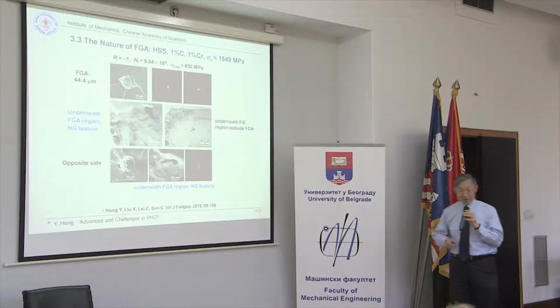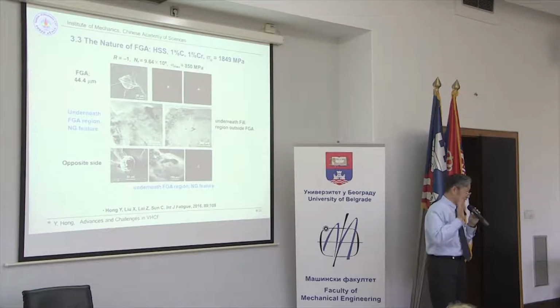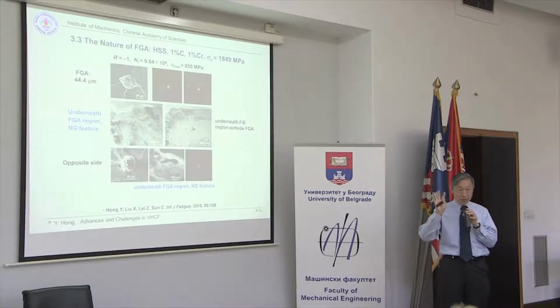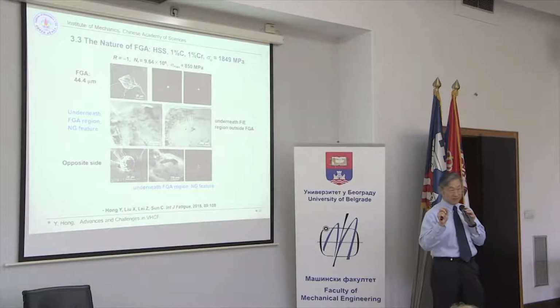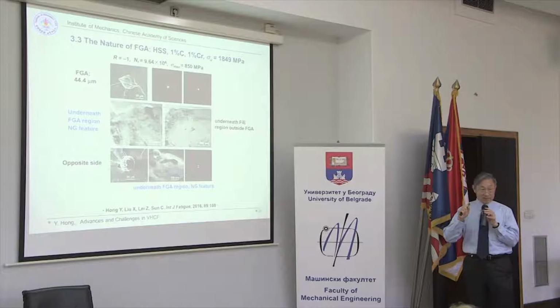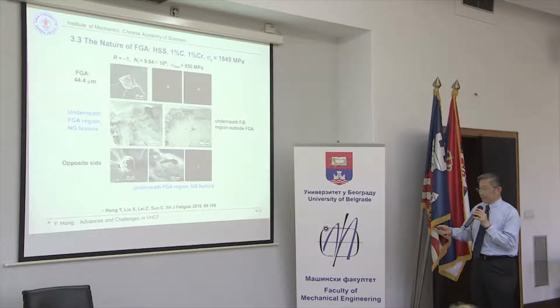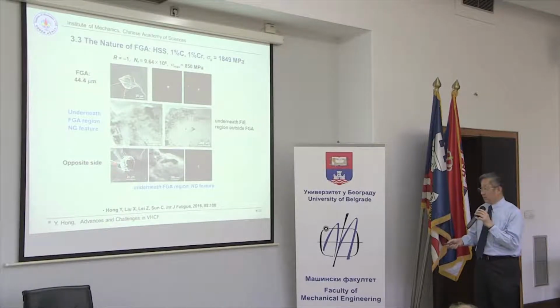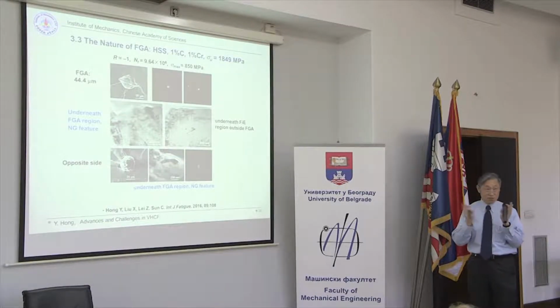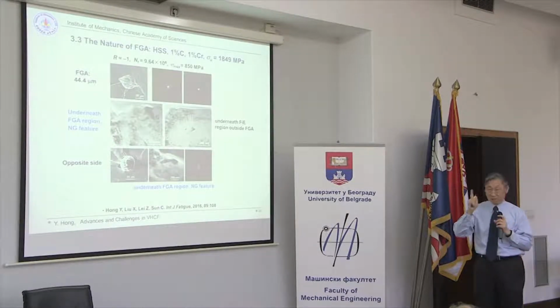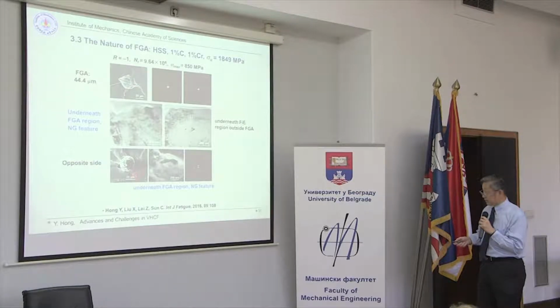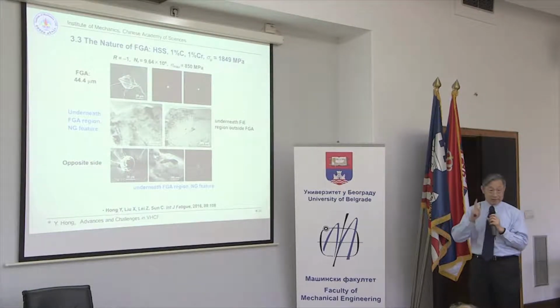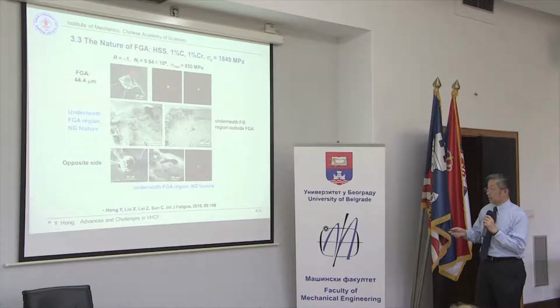And because someone said this type of morphology is just on one fracture surface, on one side of the surface, we tried to observe both surfaces. So it's an example. Here are two fracture surfaces for one specimen, which we may call positive one and negative. And we can see these two can match together. It's just the same one specimen. And we cut the FIB sample or TEM sample at the same location, at the boundary of the crack initiation region and the fisheye region.